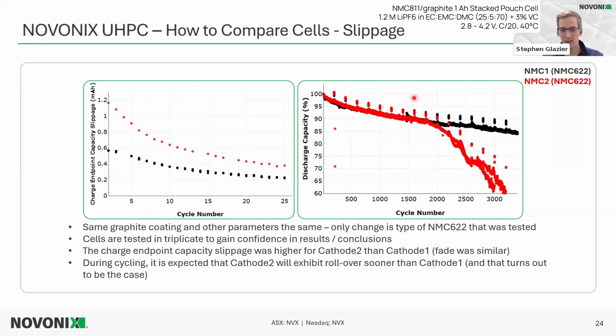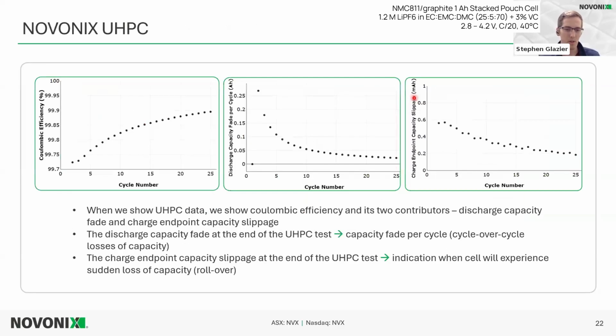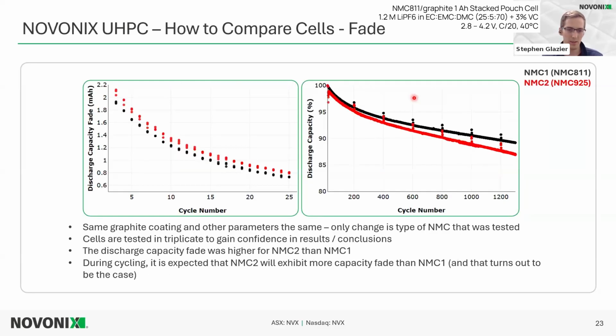Ultimately, you need an accuracy that is basically much better than the order of magnitude of these reactions happening. You need your resolution, your accuracy and precision to be much better than the rate at what's happening. If the rate at what's happening is within the noise, you'll never be able to measure it. And in modern batteries, the rates that these mechanisms happen at are tiny. They're at ppm levels. So you really do need UHPC. Otherwise, you can calculate slippage, but it's not really going to mean anything. Channel to channel, the noise and the inaccuracy will be much bigger than differences cell to cell or chemistry to chemistry.